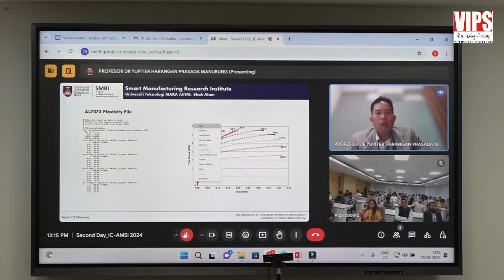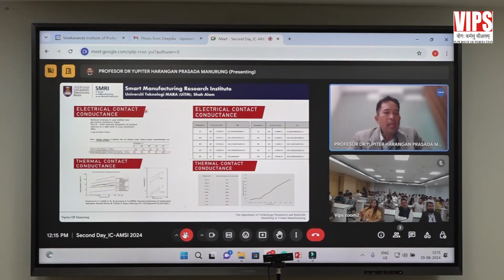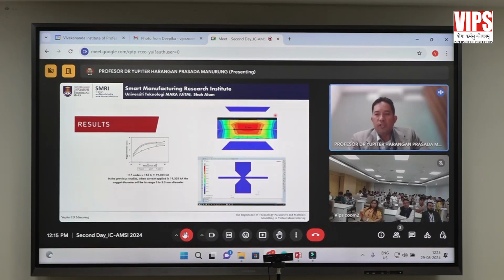We do also the flow curve, material modeling. The most important things are the contact conductance: thermal contact conductance and electrical contact conductance. These contact parameters, coefficients, are very, very important, but very difficult to determine. That's why at this stage we do research in the literature, in journals, to get these coefficients. Okay, here are the results. This is the result from the journal, 3 to 3.5 millimeter diameter. So we got here 3.2 millimeter for the nugget size.